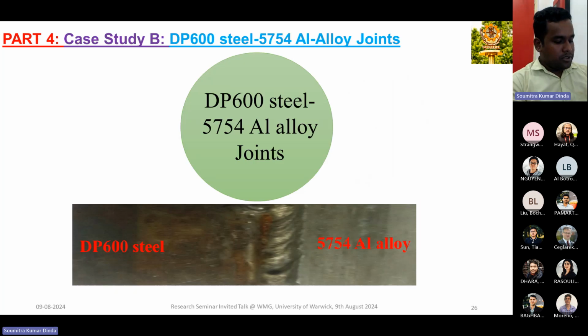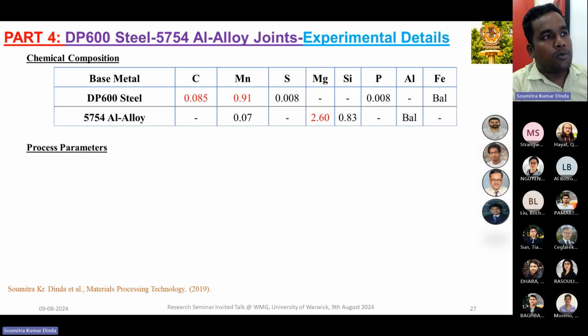So now let's move to part 4. That is the second set of material, that is DP600 steel to 5754 aluminum alloy. And this is the chemical composition of our material, where the DP steel microstructure is ferrite and martensite, with the martensite being the island in the ferrite matrix. And the 5754 aluminum has a pancake-type microstructure, where, because this is the 5000 series, the major alloying element is magnesium.